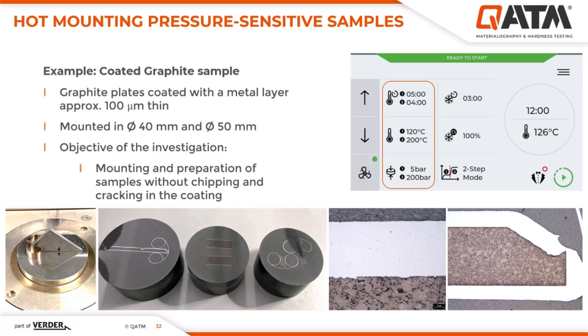After a cooling time of 3 minutes, the sample could be removed and then polished down to 1 micrometer using 1 grinding step and 3 polishing steps. Microscope images of the metal layer clearly show that the coating was not damaged during the mounting and during the preparation, and it can now be analyzed without artifacts. In comparison, using a one-step mounting process destroys the metal layer, making the analysis impossible in that case.